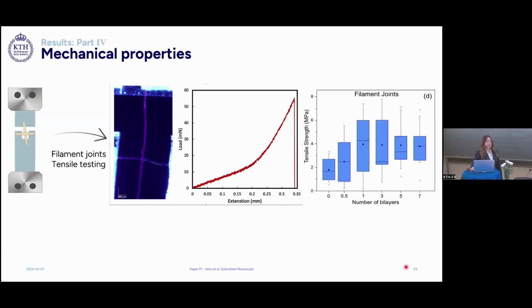The joint strength is presented in the box plot here. We can see that the average strength of the joint remains almost constant when we increase the added bilayers on the surface. However, the lower bound here increases, which suggests that the weak joints are eliminated by adsorbing more polyelectrolytes on the surface.